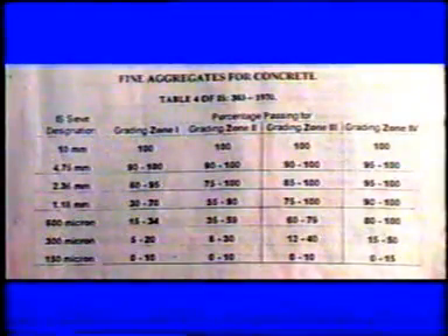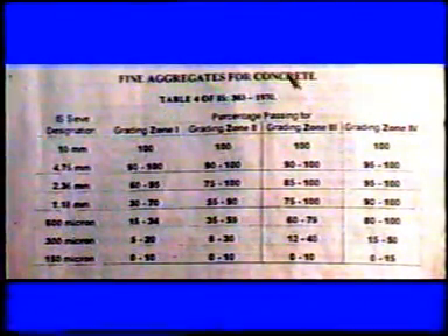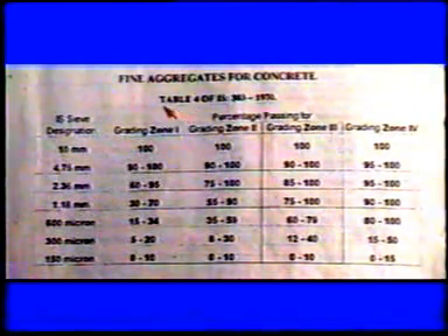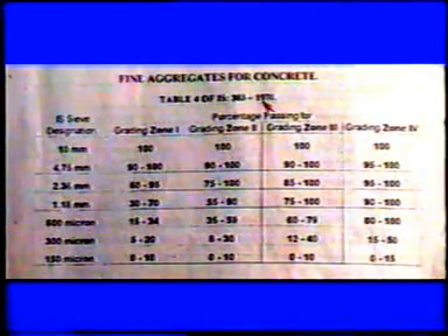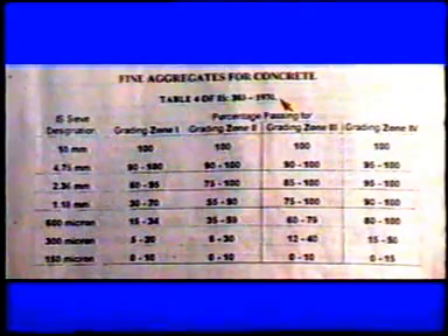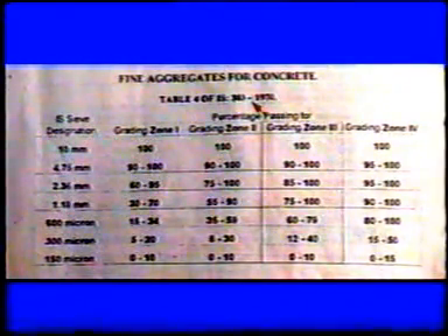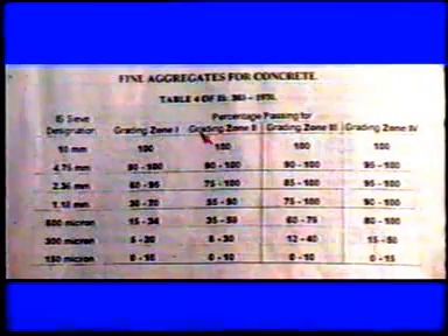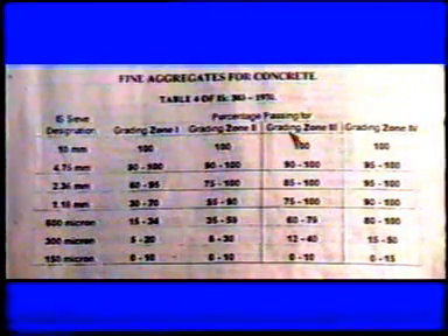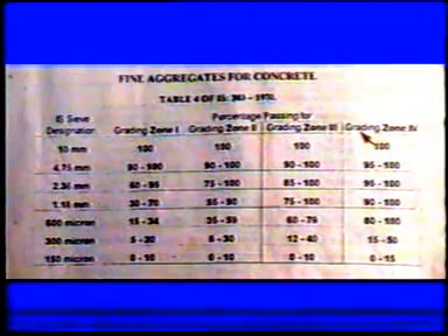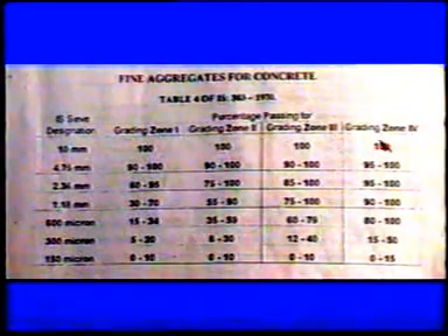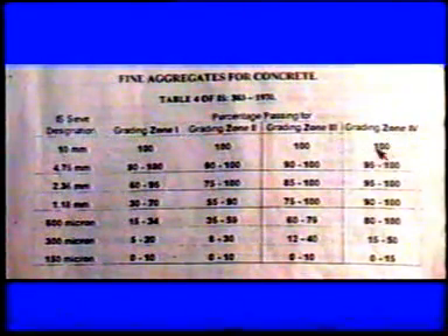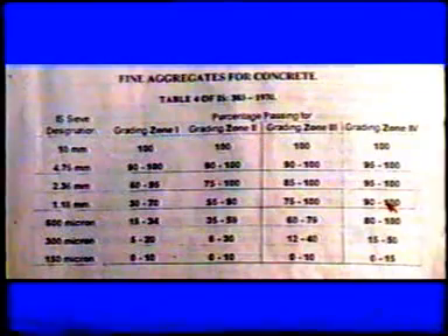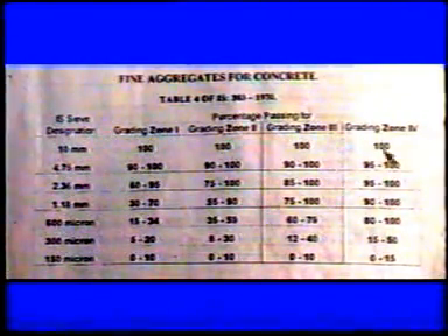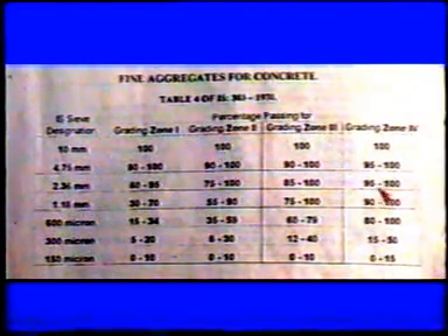This table shows the grading requirements of the fine aggregates to be used in the concreting purposes. This is as per the table 4 of IS 383/1970. The gradings have been divided into 4 zones. Zone 1, Zone 2, Zone 3, Zone 4. As you go from Zone 1 to Zone 4, the aggregate size becomes finer. Zone 4 is restricted to use in the RCC purposes.